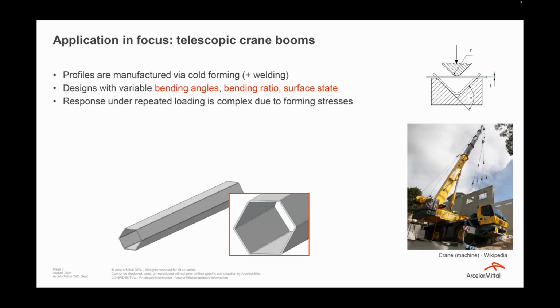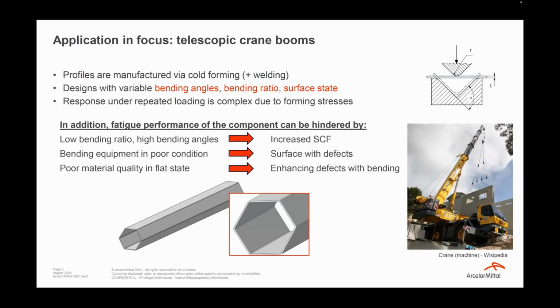And the response will be rather complicated because during forming, you are gonna generate macroplasticity in the part. You are going to generate residual stresses, so it's not immediately certain how your product will really perform. And in addition, the fatigue performance can be hindered if you consider low bending ratios or high bending angles in your designs, because it will increase the stress concentration factor. Or maybe the bending equipment that you're using is in poor condition, then it will create surfaces with defects. Once you form them, it's going to affect the in-use properties.